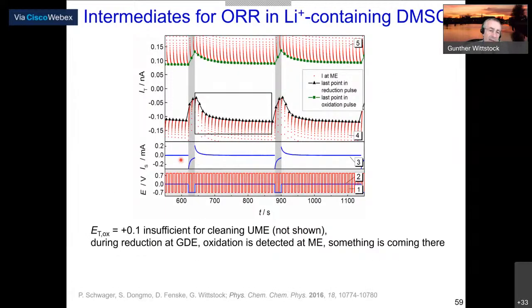So here you see another experiment where we not only pulse the microelectrode to detect the influx of oxygen, but at certain times we also pulse the gas diffusion electrode to start the oxygen reduction at the gas diffusion electrode. And if this happens, we don't expect oxygen to come to the microelectrode. And this is what we see indeed. At the moment when we start the oxygen reduction at the gas diffusion electrode, the oxygen influx in the solution stops, the current decays, and if we let the gas diffusion electrode again be at open circuit potential, then the oxygen reduction current at the microelectrode is slowly recovered.